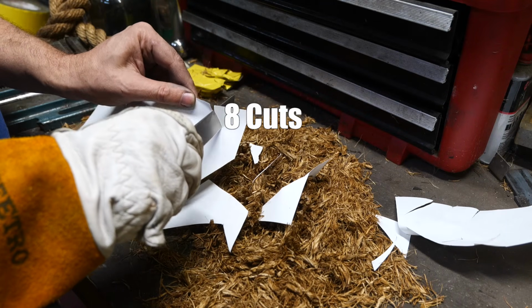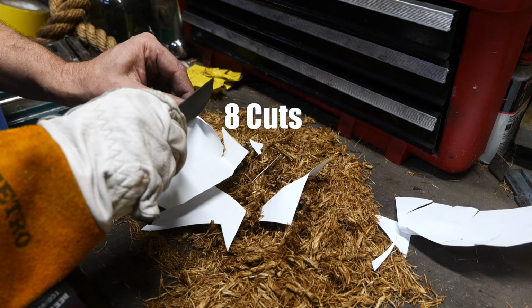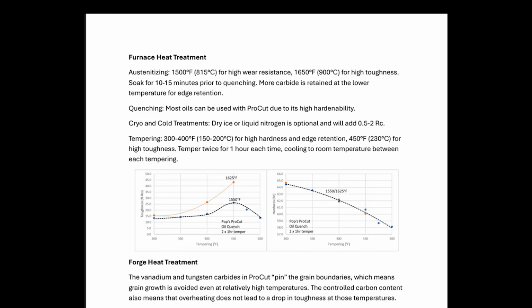So our post-quench HRC wasn't that different, and as expected, performance and edge retention went down. Remember, the advertised quench range is roughly 1500 to 1650 degrees, with the lower temperatures favoring edge retention and higher temperatures favoring toughness. I've tried this steel at 1525 and 1550 degrees in the previous video, and now 1600 degrees. What if we go down to 1490 degrees? What kind of edge retention can we get there?